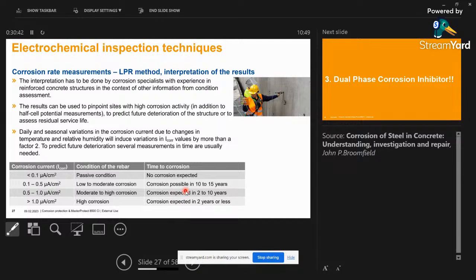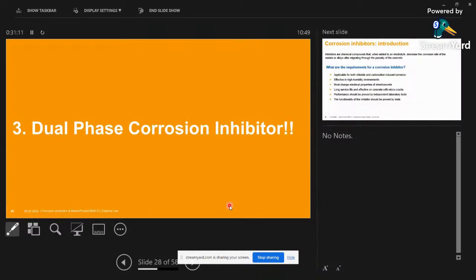So like this, it basically tells if it is more than 1 microampere per centimeter square, the condition of the rebar is highly corrosive and corrosion expected in 2 years or less. So those kind of severe damages is expected in 2 years or less. This is the interpretation of the LPR test. It's one of the best tests that can be performed, and I think it is already done in India, and there are many institutes that perform this.